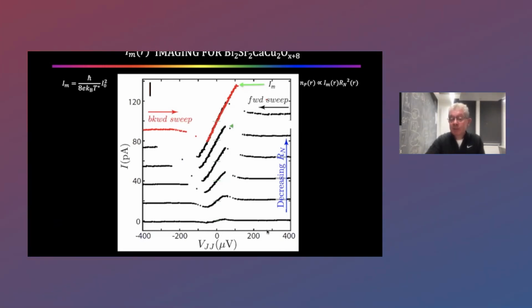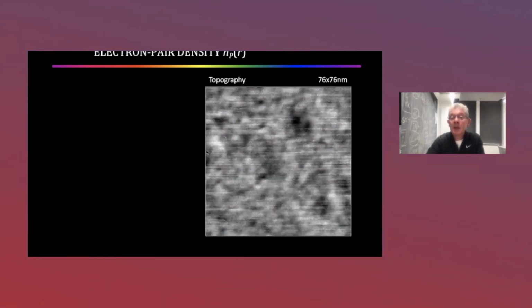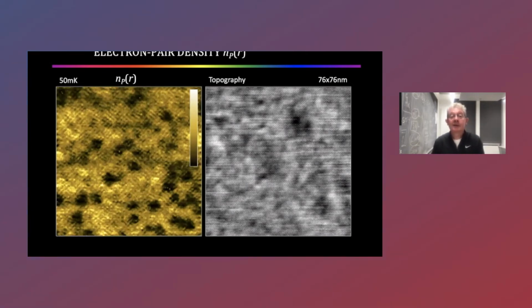So with such a tip, and now just using voltage differences of microvolts, this isn't the tens of millivolts you use for quasiparticle tunneling, it's just tens of microvolts, as you bring the tip in close to the surface, you see the pair current branch appearing quite beautifully. We were thrilled to see this. Now, what we want to measure is the maximum in the pair current as a function of location. So here's a typical topographic image of BISCO with the superconducting tip. Now, in that field of view, if we measure the maximum of the pair current at a few tens of microvolts, it looks like this at 50 millikelvin.